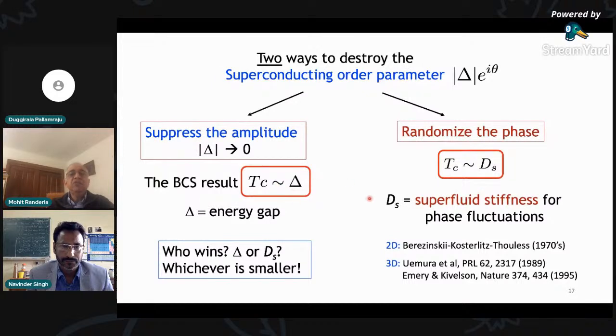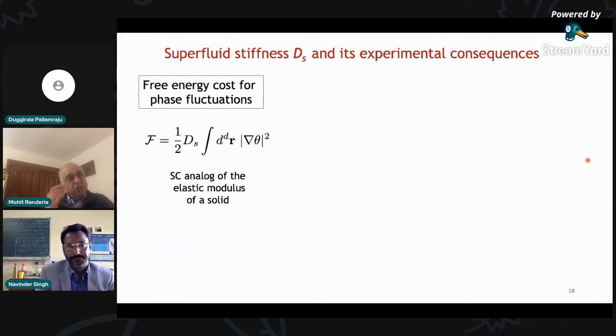Energy gap you've learned about in elementary classes. Stiffness, much less so. So let me say a few words about stiffness. The superfluid stiffness is something that governs the free energy cost for fluctuations of the phase. In a uniform superconductor, the phase of the order parameter is spatially independent, so of course you pay no free energy cost. But if you try to distort the phase, then you get a cost which goes like the gradient of theta squared. And the stiffness tells you exactly what the value of the free energy cost is. The reason we use the word stiffness in this field is because it's the superconducting analog of the elastic modulus of a solid, right? If you try to distort the solid by putting in a strain field, then the free energy increase is set by the elastic modulus.